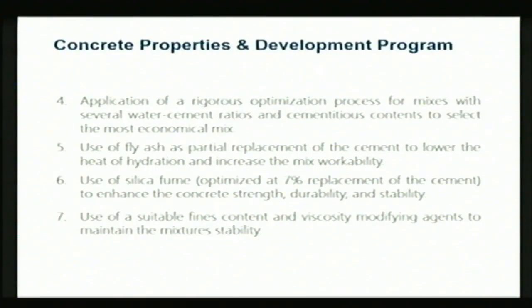And the optimization process, as I said, the contractor was looking for cost, and we wanted to make sure that we have all the ranges of water cement ratios required to address this project properly. We use fly ash as a partial replacement to reduce the heat development, and we use silica fume. We optimized it at 7% to make sure that we get the water cement ratio low enough and we get the durability and the permeability requirement. And we had to really play with the fines and the coarse content and the viscosity modifying agent to maintain the mixture stability.